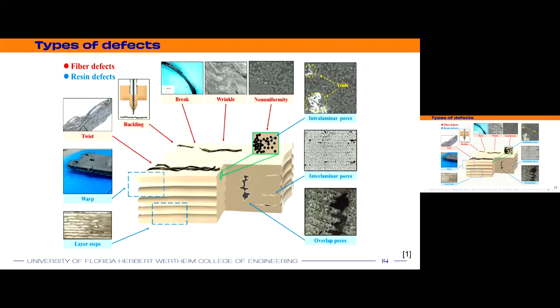And for the resin defects, there's warpage here shown on the left, because there's no mold and there are high temperatures involved. So yeah, the material tends to warp. There are layer steps, which are also common to see on the surface of a 3D printed part. And then there are 3 different kinds of pores, which are also highly problematic, because there can be more than 10 volumetric percent of pores within the part. So intralaminar pores, and overlap pores, as shown on the right.